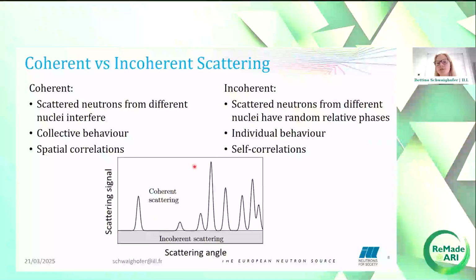Incoherent scattering, on the other hand, is the phenomenon when scattered neutrons from different nuclei have random relative phases and there is no interference. Therefore, incoherent scattering gives access to individual behavior and self-diffusion, like self-correlation. This is quite important for studying QENS of proton conductors or hydrogen diffusion in general, since hydrogen is a very strong incoherent scatterer, which means that QENS can be used to study the self-diffusion of hydrogen.